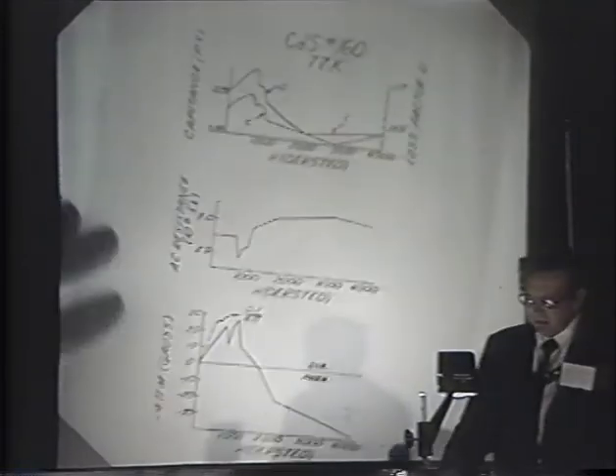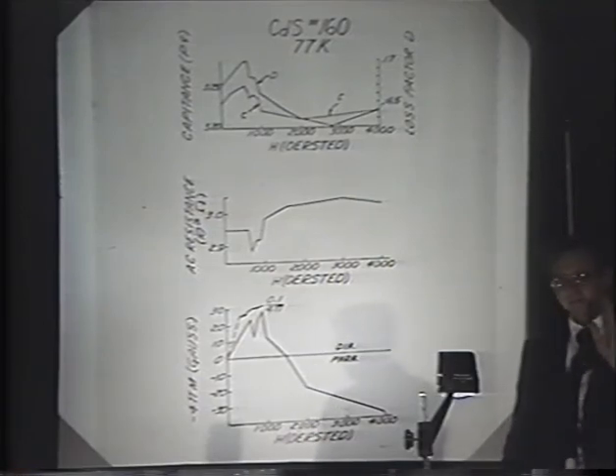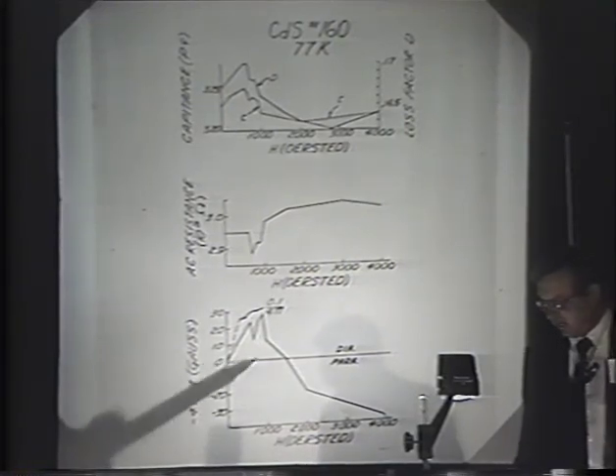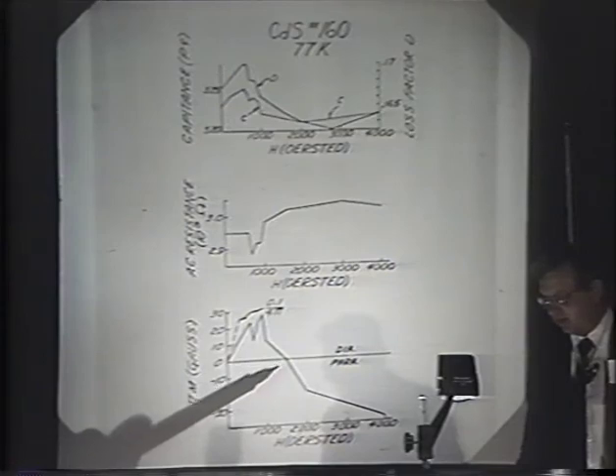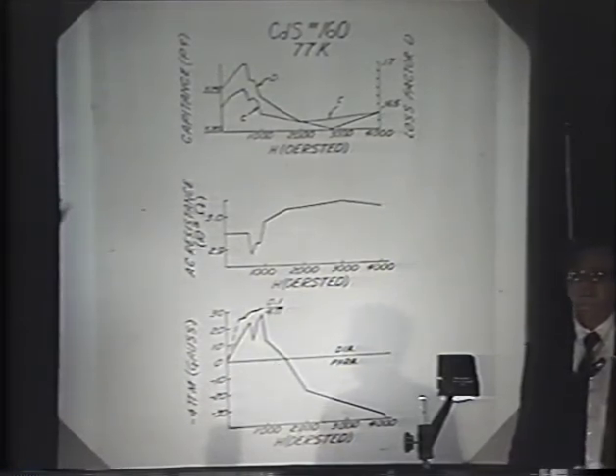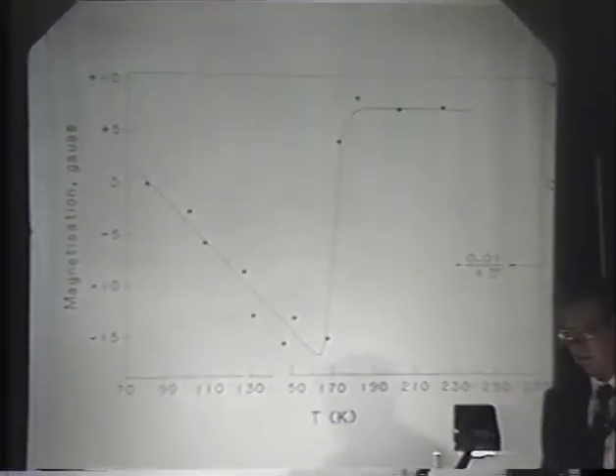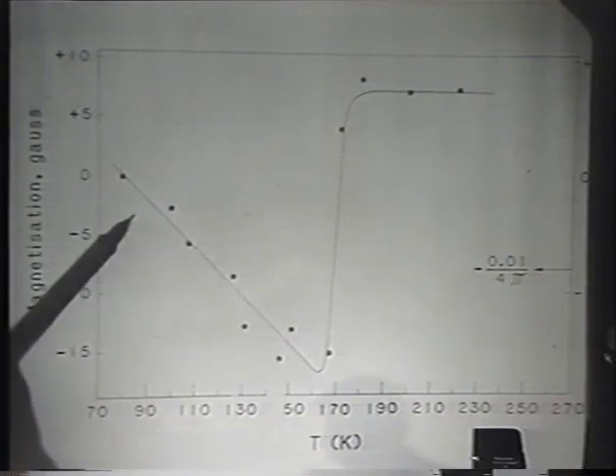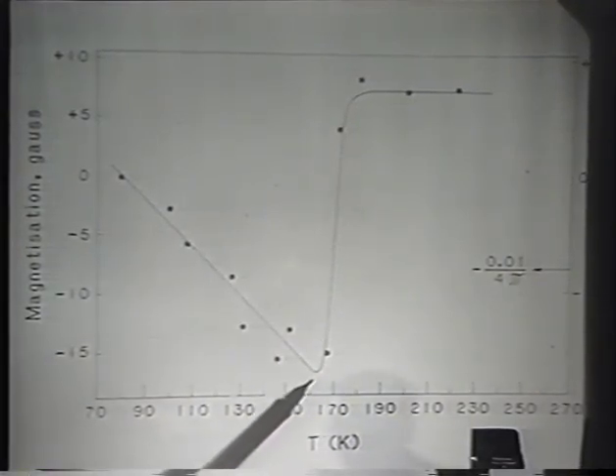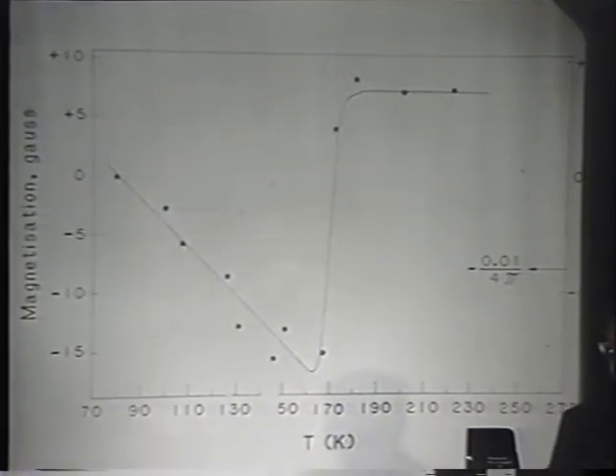Now, unfortunately, the microstructure that resulted precluded us ever measuring zero resistance. And our specimen looks like little platelets like this inside the Wurtzite matrix. But we were able to show measurements such as these, where on the same specimen and simultaneously we measured a collapse of the exclusion, penetration of the flux, and electrical changes that were consistent with superconducting regions becoming normal. How high did we see? What is this large diamagnetism? Here is an example which is a Meissner effect. We have a magnetic field of 1 kilogauss, and we're heating the specimen up, and it's becoming more and more diamagnetic, and at this point it switches from diamagnetic to paramagnetic, and we would argue that we see a TC of 170.